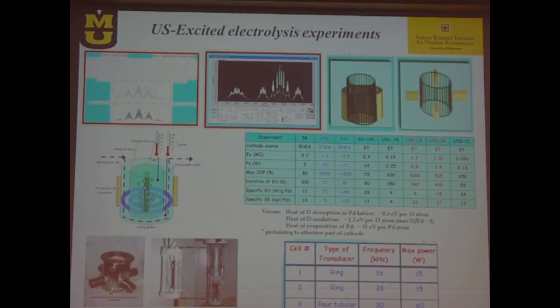Also, these cavitations are developing the surface to be the surface which is needed for excess heat to happen, but there are many other ingredients which I'll show immediately. So definitely from 20%, we increased the reproducibility to 40%, and it's not minor.